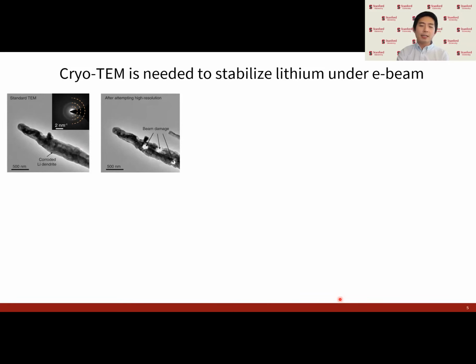That's because lithium and similarly lithiated compounds are air reactive and weakly bonded. So that means that during sample insertion into the TEM, during the brief air exposure, battery materials, such as this piece of lithium, will corrode with air and water. And that compromises any of your interesting chemistry as you instead form lithium oxides and hydroxides. Attempting to do any high resolution imaging of the specimen results in holes being drilled in your sample from the electron beam damage.